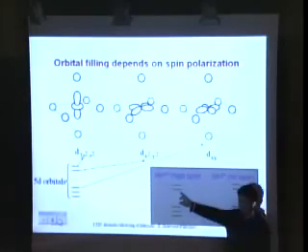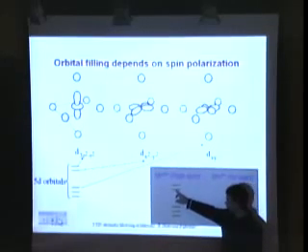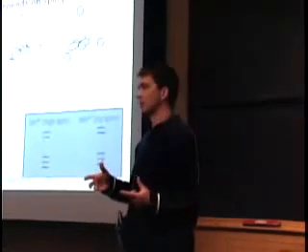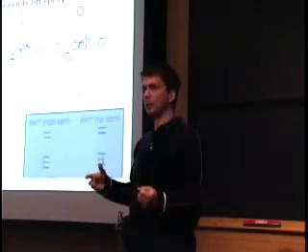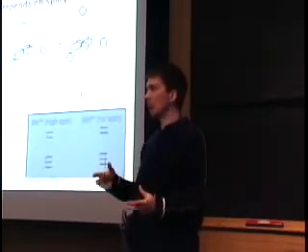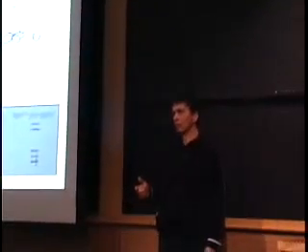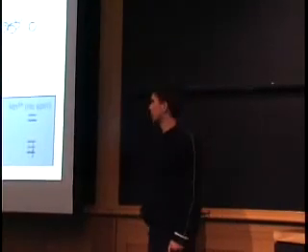So these two ions have different chemical properties because the electrons occupy different orbitals. These are different d orbitals. And so this orbital points in a different direction, for example, than this one. So by spin polarizing, you create essentially a different ion. It's not really an issue of magnetism, because magnetic effects tend to be small in materials, but it's the fact that you create chemically a different ion because you fill different levels. That's really why these energy differences are so big.